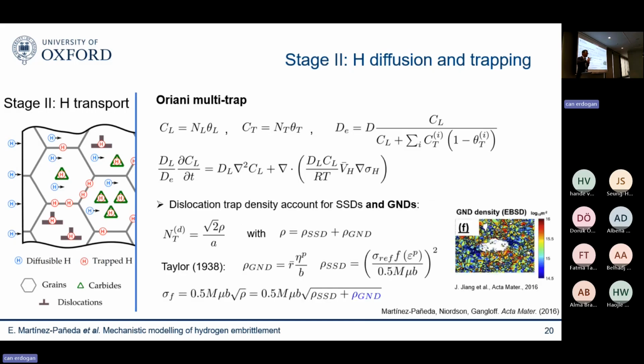And I'm not going to spend too much time on this, but one thing that I should say is that one aspect that I think the community has overlooked is that if you're interested in knowing how much hydrogen you have in your dislocation field, you not only care about the statistically stored dislocations, but you must also take into consideration GNDs, geometrically necessary dislocations. We heard in the previous talk about the importance of GNDs, and these are very important in hydrogen because GNDs, due to plastic strain gradients, dominate near cracks and inclusions, and we can see this experimentally.